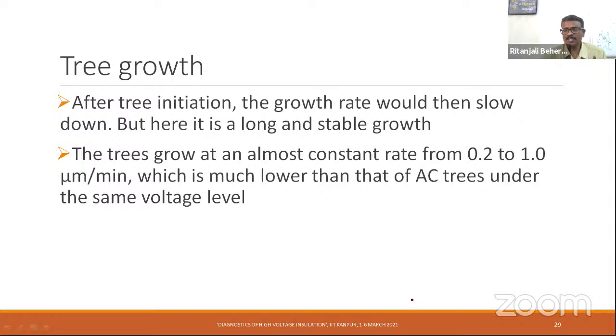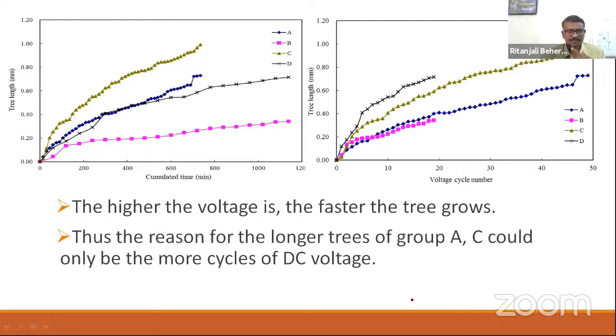So there is a thin branch is one observation. Number two, steady and slow growth is another observation. This is actually what I mentioned: the higher the voltage, the faster the tree grows from the first plot. And the second one says the reason for the longer tree length is due to the more cycles of voltage application. In fact, here it was about 49 cycles that was applied, and here it is 19 cycles, if I remember correctly. So this increase depends on the number of cycles. So there are two observations that we can make. Tree grows due to the higher applied voltage, and also due to the more number of application of the cycles.